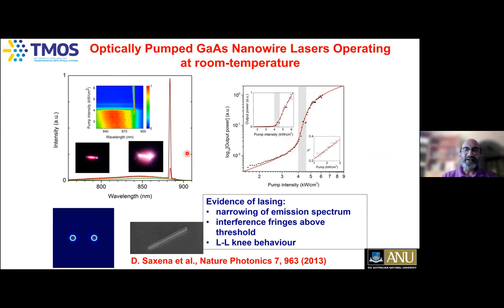In fact, Drew Saxena measured these interference fringes experimentally and simulated them, and we were able to match them very well. This work was published about 9 years back in Nature Photonics. These are the first gallium arsenide nanowire lasers operating at room temperature. Ultimately, if you do some science, you may end up making lasers that operate at very low temperatures, which may not be of interest for industry, so it's important that these operate at room temperature at least. We are planning to use these lasers for a wide variety of applications, for sensing, photonic integrated circuits and a range of things.